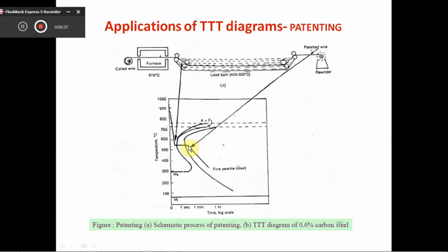The process is mainly used for spring wires, ropes, etc. The higher the soaking temperature, which is always above the austenitizing temperature, the greater are the stresses developed, making the steel prone to distortion and quenching cracks. So that may lead to the formation of some defects. As low carbon steels can be drawn heavily in the annealed condition, the patenting heat treatment is not employed for such kinds of steels.